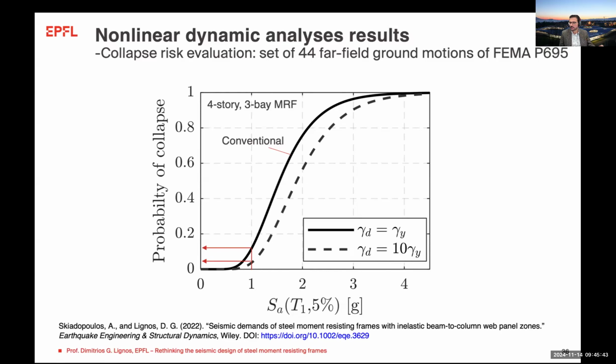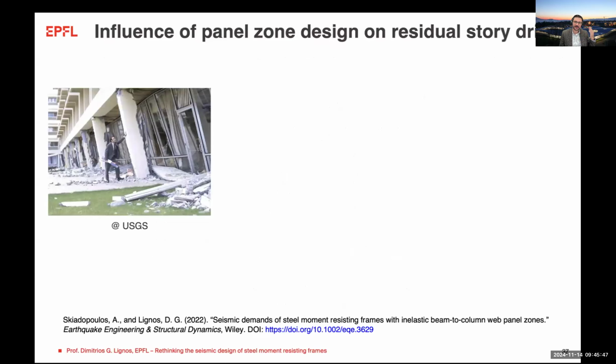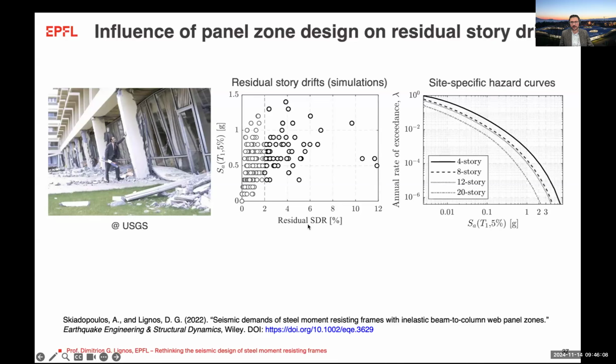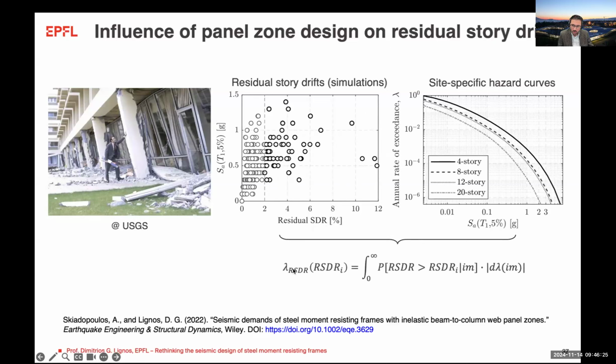But in my view, the biggest benefit is if you're looking at intensities that essentially impact the residual drift of the system, because as we know, when you're looking at code-compliant systems, we worry if this would remain at a large residual drift, and then potentially demolition would have to be imposed. So here, in this case, if you want to assess the potential of demolition, based on this analysis we did, we kind of collected residual drifts for all 32 designs. And if you essentially work in the framework of performance-based design, you can compute what would be the rate of having demolition by developing what we call demolition hazard curves by integrating the site-specific hazard curve over a residual story drift curve.